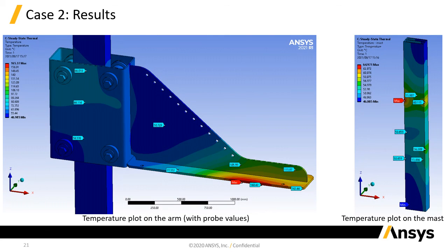We look at the temperature plots as a result of that. We can see that here on the carriage area, as you saw with ohmic loss, there's a significant reduction even here in the region where the bus tubes run across the carriage. And if we look at the end of the mast there, where there's no shielding and the bus tubes are running across, we're getting essentially the same temperature as before. Okay, so just really again highlighting how localized the effect of the shielding is.